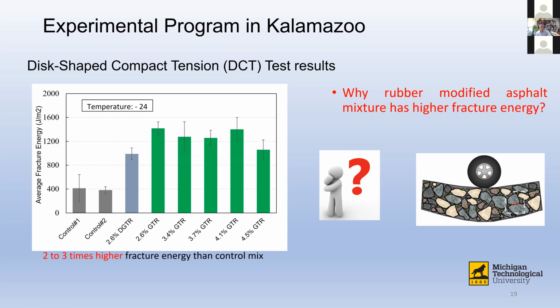What does that number tell us? It tells us that with rubber material inside, the fracture energy is going to be 2 to 3 times higher than the control asphalt we're using. So that really means there are a lot of unique features for that. That means the rubber asphalt has a lot of advantages. That is something I'd like to show here. Of course, it gives us some confidence that when this type of material is used in a cold climate like Michigan, the fracture resistance should be really good compared with the regular asphalt we are using today.